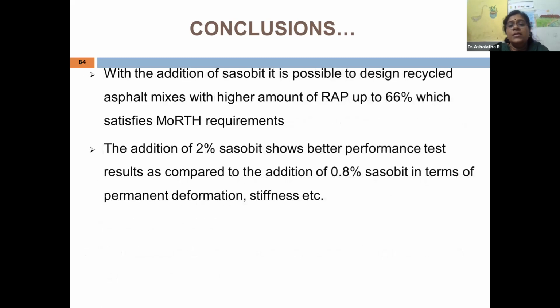And with the addition of Sasobit, it is possible to design recycled asphalt mixes with a higher amount of RAP, up to 66%. Of course, it's on the higher side, so don't take it as a final word. Which satisfies the MoRTH requirements, and addition of 2% Sasobit shows better performance test results as compared to the addition of 0.8% Sasobit in terms of permanent deformation, stiffness, etc.